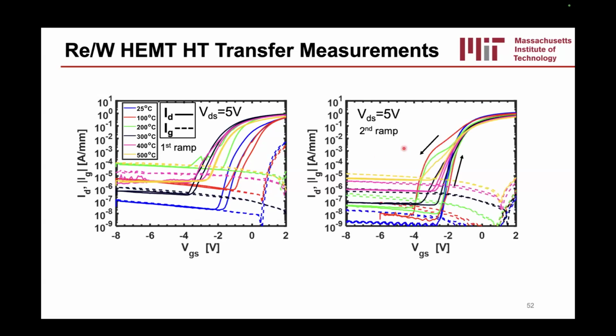Additionally, if we do a second round, we can see this time that all of the transfer curves look more or less identical. The threshold voltage change is very marginal. There is a significant amount of hysteresis, though. That's what these bumps here are, but we suspect that indeed the metal is working very well at high temperatures.